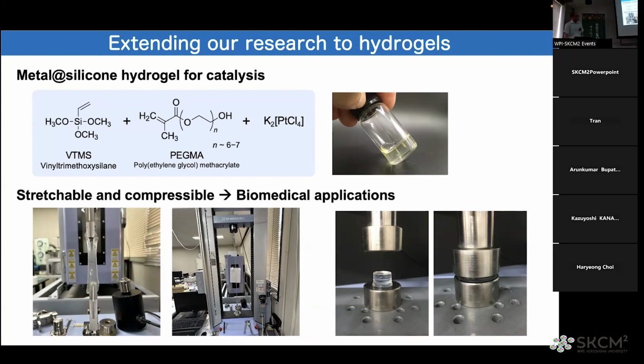Okay. So now we are trying to use the materials as a solid catalyst in organic synthesis, like hydroxylation reactions and also carbon-carbon coupling reactions like Heck reaction. Very good. Now we found this can be a very good catalyst because the network has flexible nature, so it is quite dynamic. Then they show a good reactivity against the substrates.